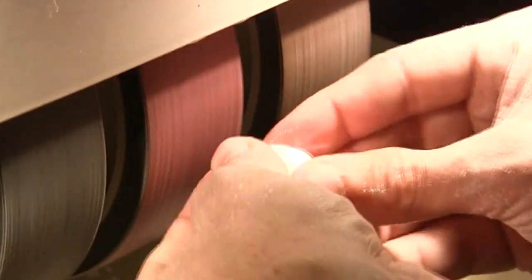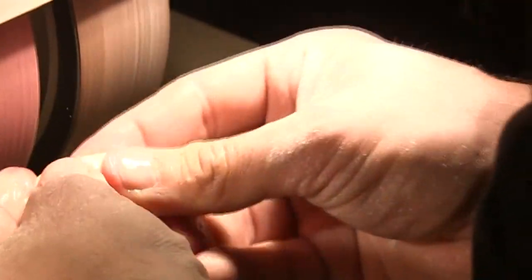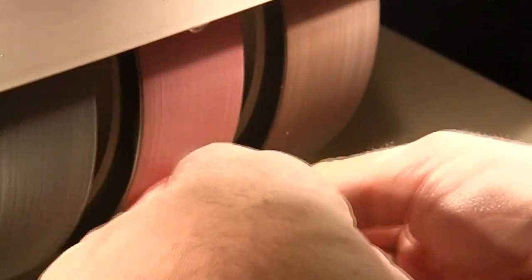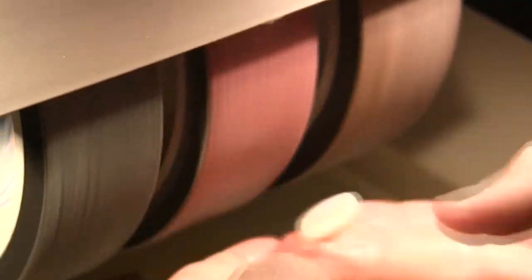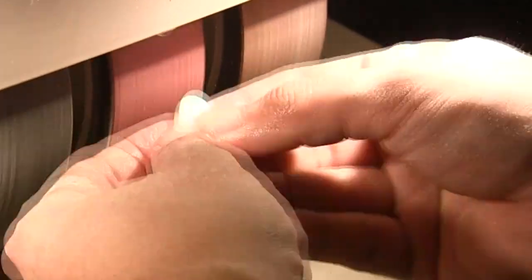Opal isn't a crystal. Even crystal opal isn't a crystal. It's just crystal clear, I guess. It's actually a gel, a hydrosilica gel. Australian opal, on average, is between 3% and 7% water. It can be a lot higher. And the higher the water amount is, the more chance the opal has of crazing. Crazing is when you get a crackly surface across the top of the stone, and it renders your stone worthless. Or in cases of large cool stones, it might be good as a specimen, but it's not going to be worth a hundredth as much as it would have been if it hadn't crazed.